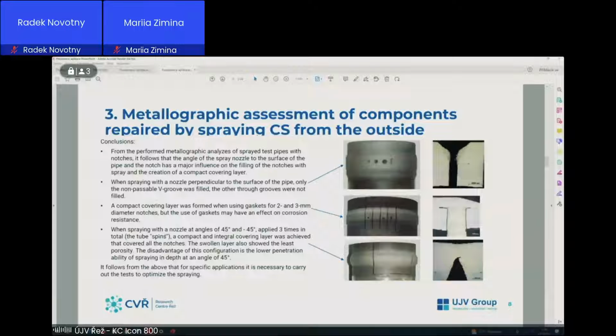minus 45 degrees, applied 3 times in total. We then received compact integral covering layer, which covered all the notches. The layer also showed the least porosity. The disadvantage of this configuration is the lower penetration ability of spraying in depth at angle 45 degrees. You can see that here. This angle is 45 degrees. So it follows from the above that for specific applications it is necessary to carry out the test to optimize spraying.